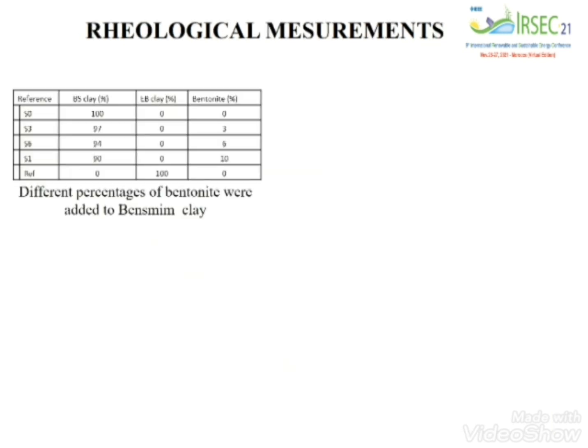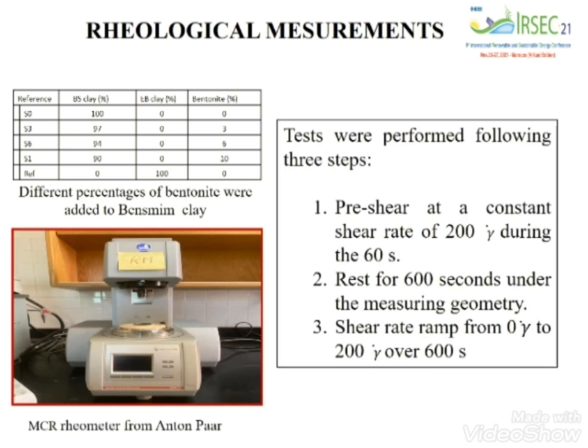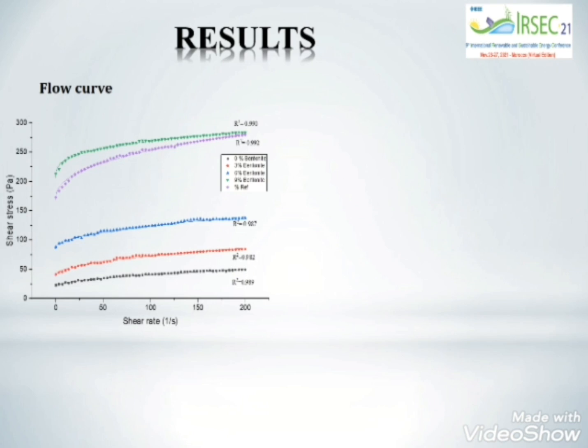So now let's move to the next part, which is the rheological measurements. Different suspensions were prepared using different percentages of bentonite, as you can see in the table, and the tests were performed using an MCR rheometer from Anton Paar, following three steps as you can see on the screen. The obtained flow curve shows that all samples show the same behavior.